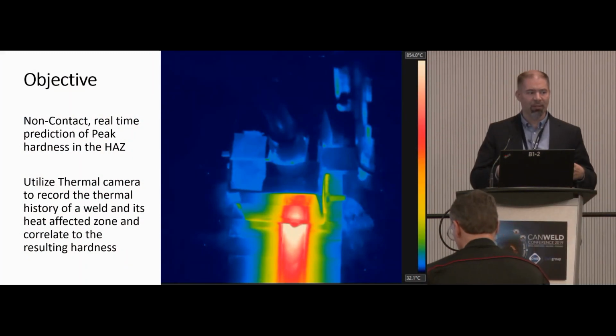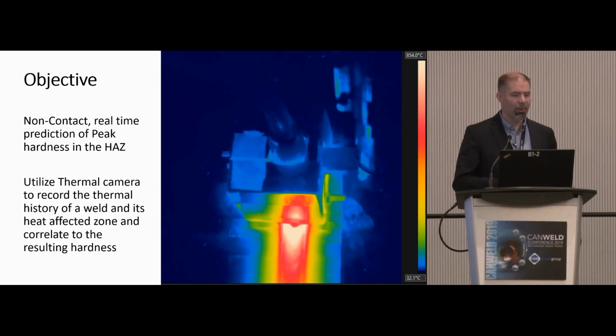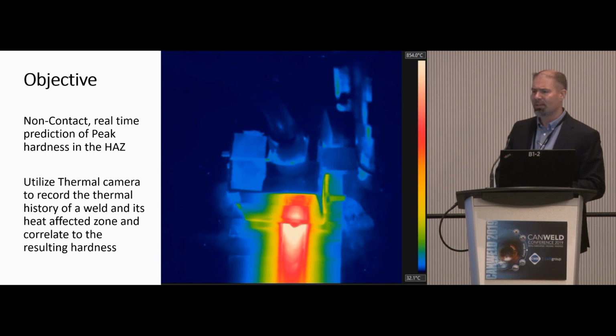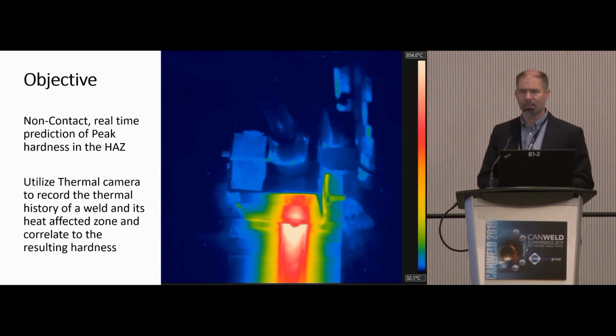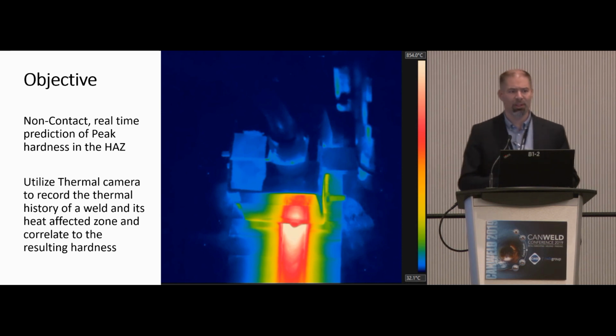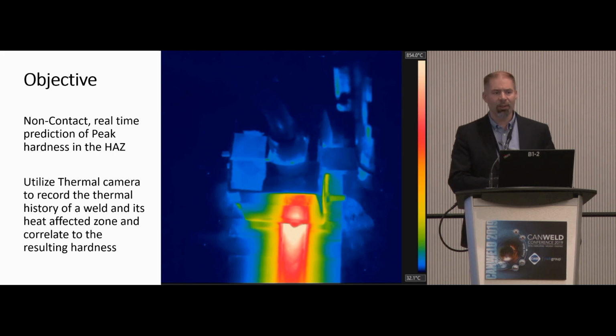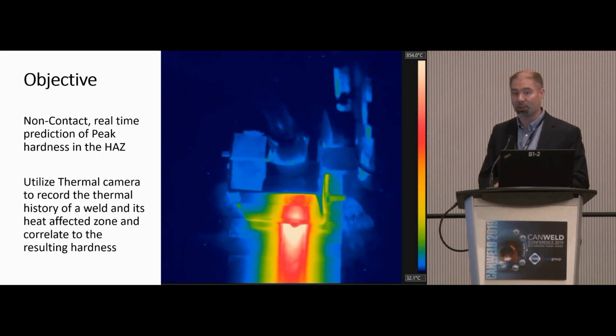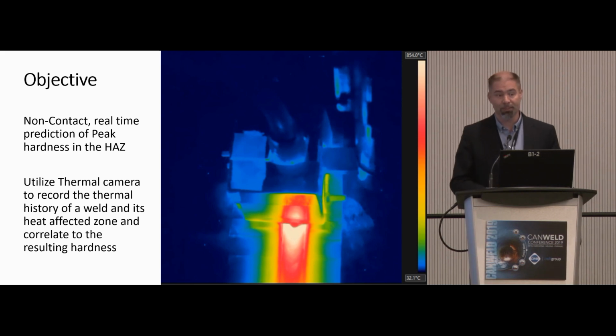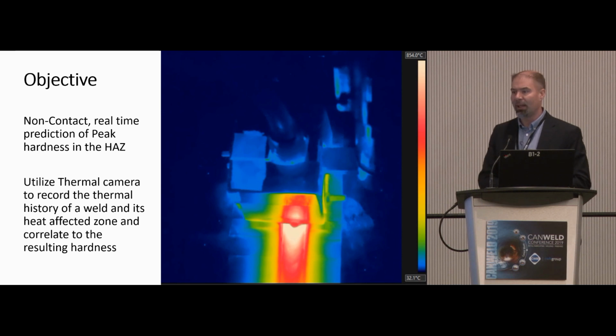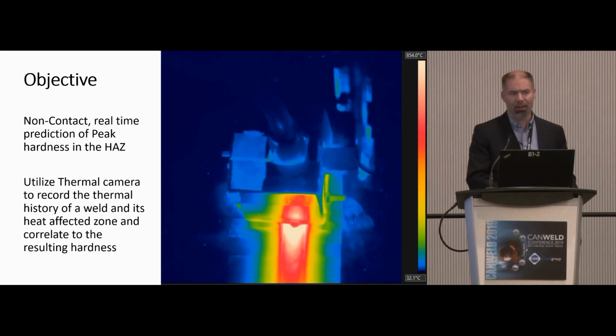So ultimately, the objective of this research is to predict the peak hardness in a heat affected zone. Ultimately, that's what we're after. Standards that are applied to a number of industries require maximum hardness values in the heat affected zone. We have to keep under those. But then on the opposite side, when dealing with quenched and tempered steels for different applications, for hard rock mining, for example, you need to ensure that you're not softening your heat affected zone too much, because the high hardness values of the base material need to be maintained in the heat affected zone and in the weld. So it's a fine balancing act, and you need to find that Goldilocks zone where it's not too hard and it's not too soft and it's just right.